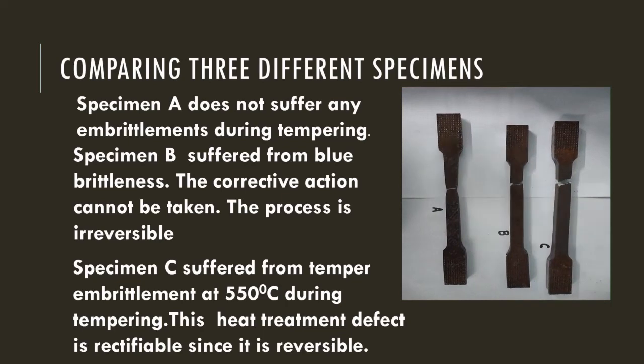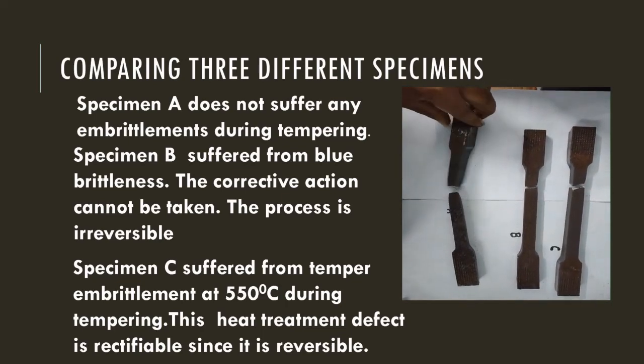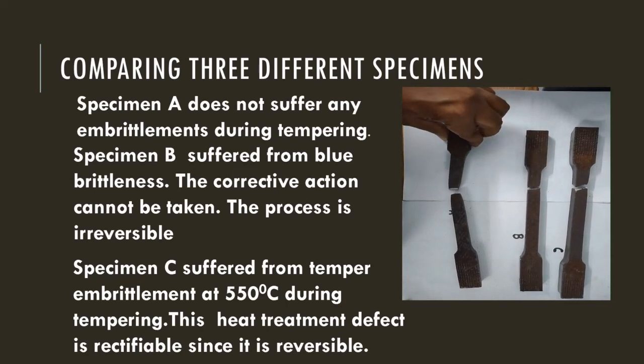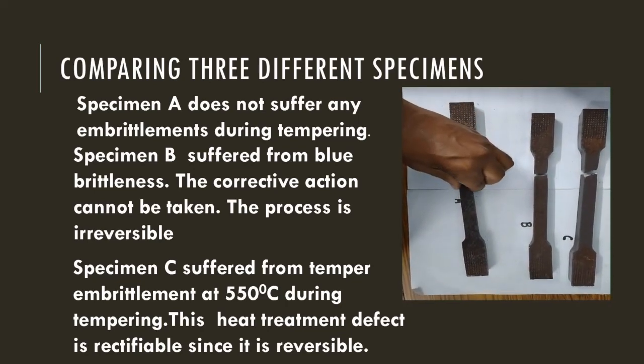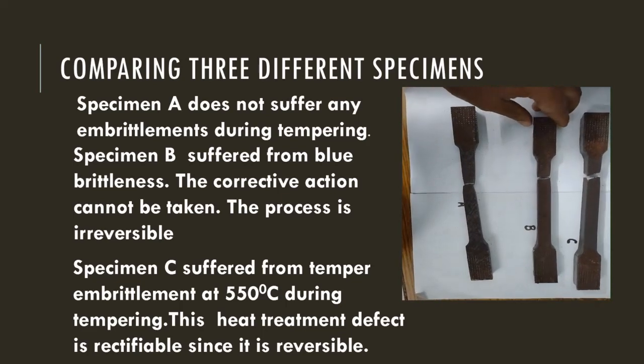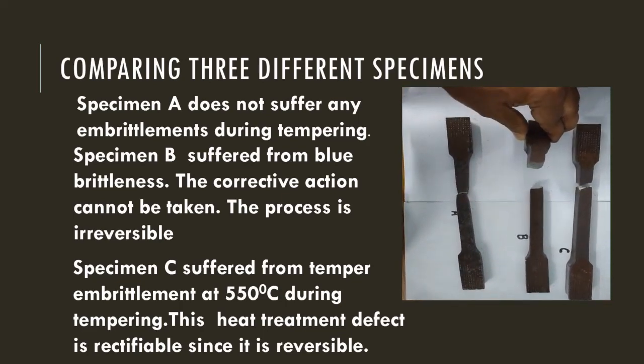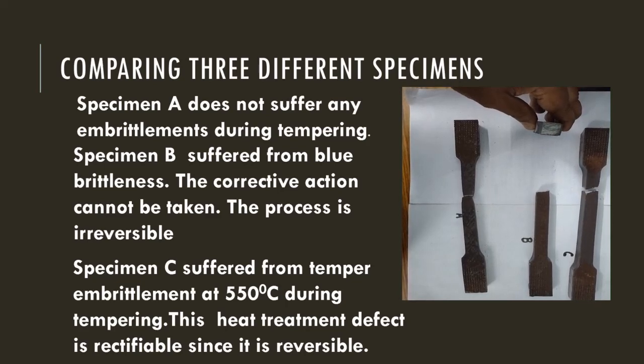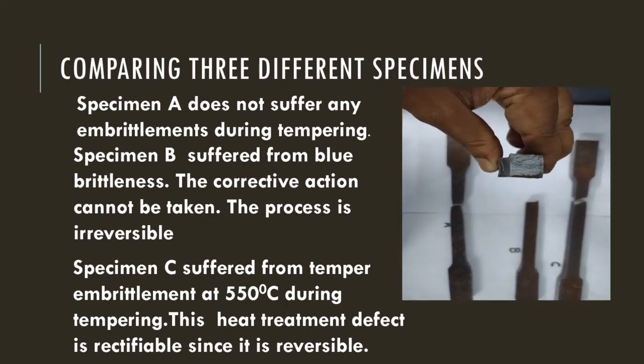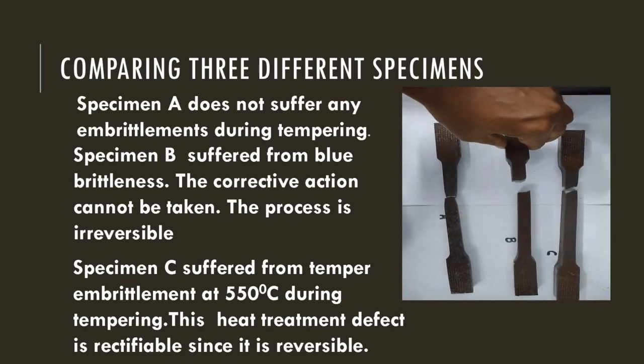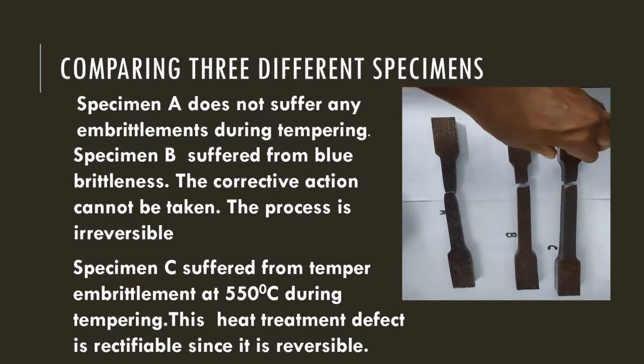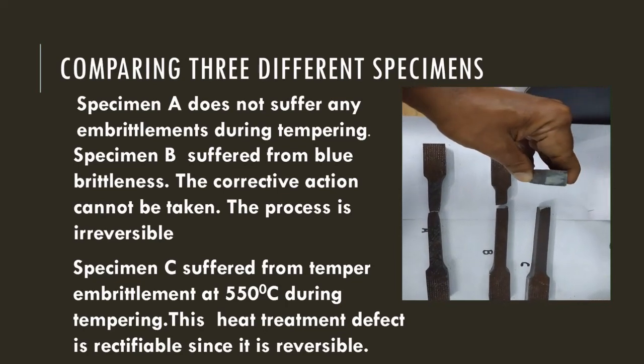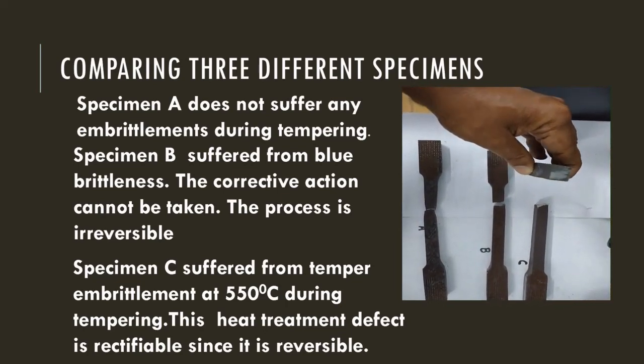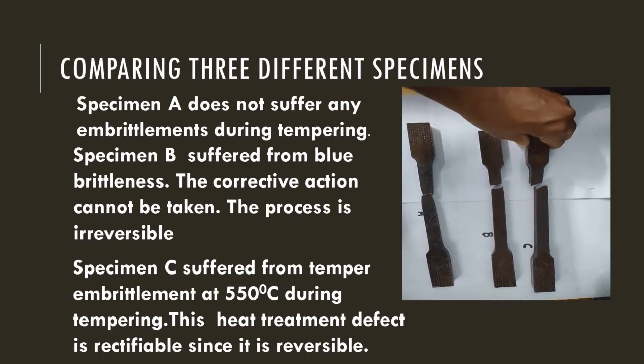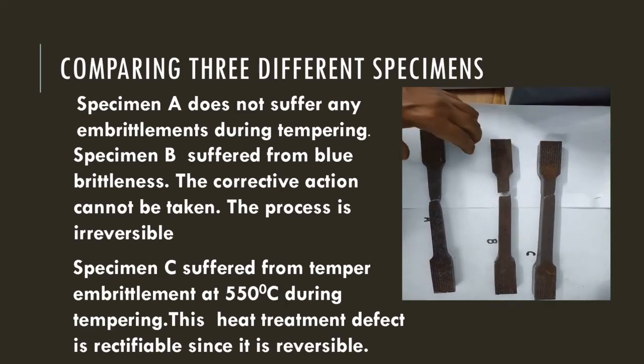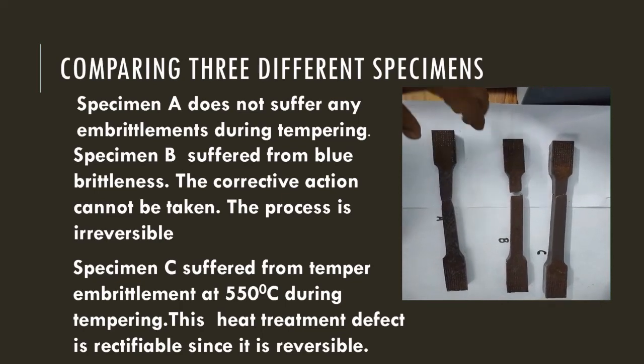For our experiment, let us take 3 specimens. Specimen A did not suffer any embrittlement, so the specimen has very good elongation to fracture, as you can see from the figure. Specimen B suffered from blue brittleness, the corrective action cannot be taken, the process is irreversible. Specimen C suffered from temper embrittlement at 550 degrees centigrade during tempering. This heat treatment defect is rectifiable since it is reversible. So you can see the 3 tensile specimens, how they behave.